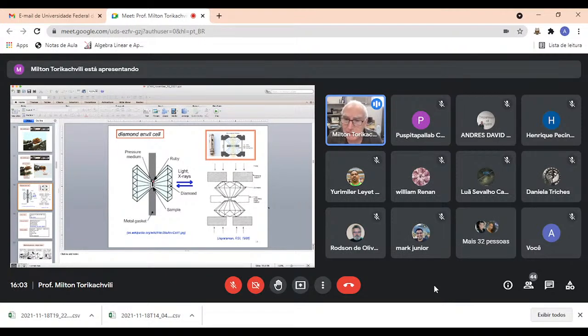So the way you do it, you put a metal gasket, about 300 microns, 0.3 millimeters, in between the cullets. Then of course, the diamonds have to be in a structure like this. This is a beryllium copper structure to hold it. So they should be lined up with each other. Now you pre-stress, you indent the metal gasket. In this case, it is stainless steel. You indent it, and since diamond is so much harder than steel, the steel is going to acquire the shape of the diamond. Then you open it up, drill a very small hole in that metal gasket, and that's going to be your pressure vessel. That's where you're going to put your sample and your pressure transmitting medium, and then apply the force, lock the force in, and